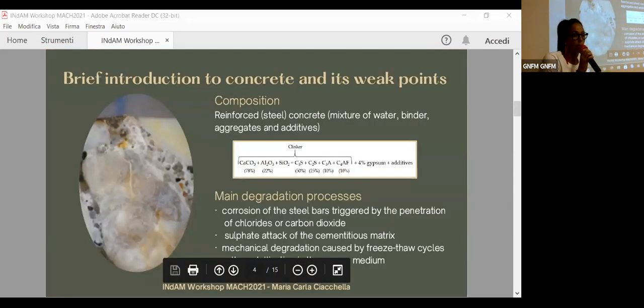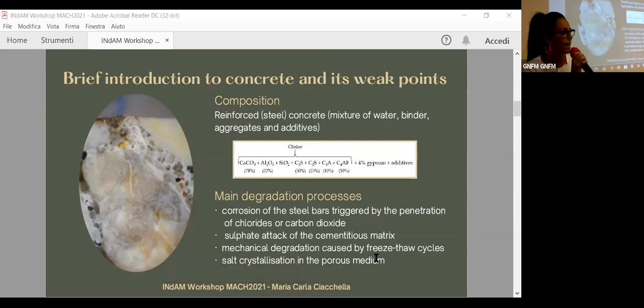A brief introduction about concrete. Of course, we generally speak about reinforced concrete, for the presence of steel, which is responsible for the tensile strength, and concrete, a mixture of water, additives, aggregates, and binder. Since concrete is not eternal, it suffers many degradation processes. First of all, the corrosion of the steel bars, a phenomenon that could be triggered by the penetration of chlorides, and the carbonation, the sulfate attack on the cement matrix, but also the mechanical degradation caused by freeze-thaw cycles, especially in high latitudes. And another phenomenon that I will explain better, which is salt crystallization in the porous medium, generally considered only for natural stones.